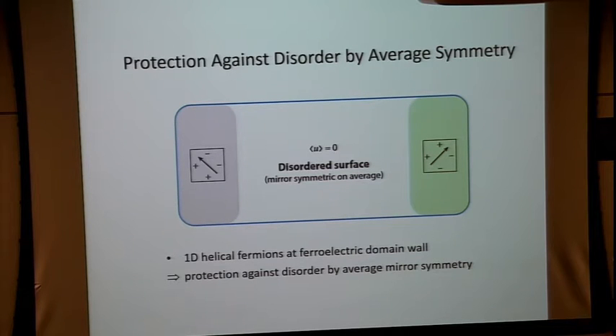It's not the same argument you and Charlie make for topological insulator with statistical time reversal. It's exactly the same for statistical time reversal. In that case, the system is self-tuned to a critical point between different Chern states. So in the case of a strict 3D topological insulator with time reversal symmetry, the surface is metallic because of the anomaly. And here, it's metallic because of the self-tuned critical point. This ferroelectric polarization is approximately quantized, but not exactly. We can discuss later.